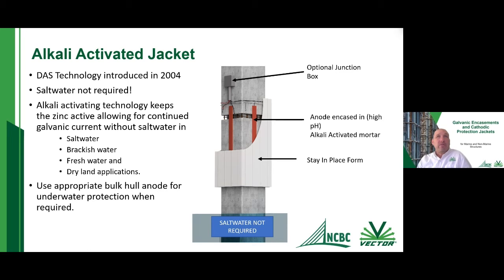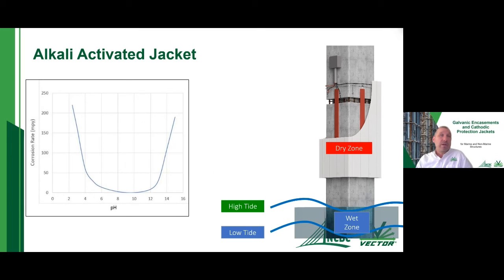And again, dry land, of course. If you're using this in a brackish water environment, you can use a bulk anode for protection, because you can extend this jacket down into the water. Another option is you can use this activated jacket with one of those Tidal Plus jackets as well. So you could use the Tidal Plus jacket in the salt water or in the water portion, and then as you move up higher in these elevations where you don't have access to the salt water, you can then use the alkali activated jacket in these elevated portions.